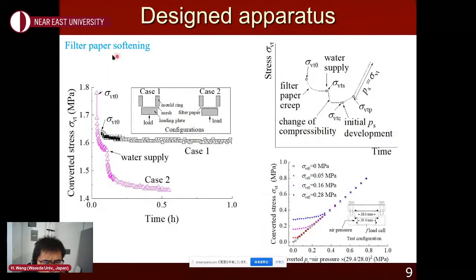Another thing is the filter paper softening. It's different from the filter paper compression. When we apply a filter paper under the specimen, the stiffness of the filter paper will reduce because of the water. Once the filter paper absorbs the water, it becomes soft. So if we apply an initial load here, because of the softening deformation of the filter paper, there will be a reduction of the stress. So this is another problem.